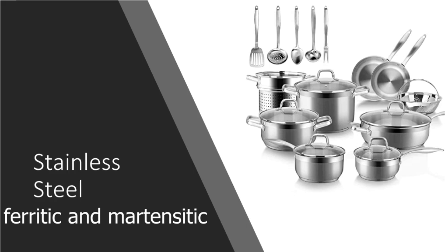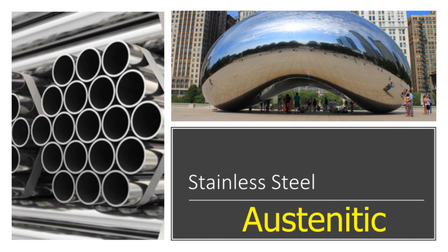Austenitic stainless steel contains chromium and nickel, little or no carbon, and cannot be hardened by quenching. But it readily work hardens while retaining much of its ductility. For this reason it can be work hardened until it is almost as hard as a hardened martensitic steel. Austenitic stainless steel is somewhat magnetic in its work hardened condition, but non-magnetic when annealed or soft.